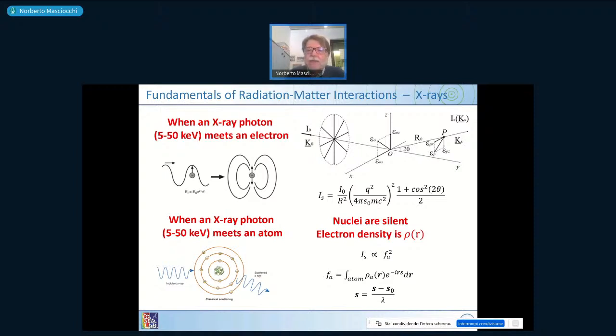There is a theory, the Thomson scattering theory, which uses some vectorial properties, and says that if you have an impinging beam on an electron, it diffuses around itself an amplitude, and this amplitude is related to the original amplitude. So the intensity which is impinging is linearly related to the scattering intensity. But there are other terms. One is this term to the right, which is a trigonometric term related to the 2 theta scattering angle. One is r squared, which is the distance at which one observes the material. So basically, if you go far away, the light becomes dimmer and dimmer. But then you have a squared term which contains only fundamental terms in physics.